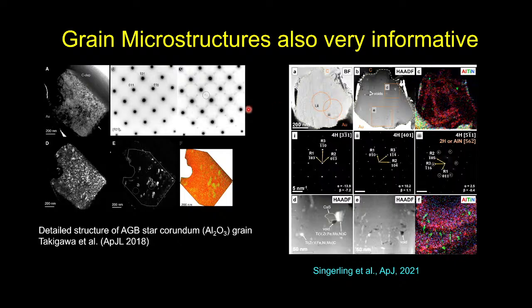And what we're looking at here is another one of these aluminum oxide grains. And a postdoc that was working with me and another colleague named Aki Takigawa used an ion beam to cut a thin slice through this micron-sized grain to make a very, very, very thin slice of it and put it in the transmission electron microscope. And so these spots here, if you're not familiar, are an electron diffraction pattern. So it's how electrons are basically diffracting off of the crystal lattice. And it's hard to see, but these big black dots are what you expect to see for a pure aluminum oxide grain. But there's other little spots in here that are related to crystal damage. And you can see that in these images here, that there's crystal damage, and it's also associated with magnesium. The green bits are magnesium.